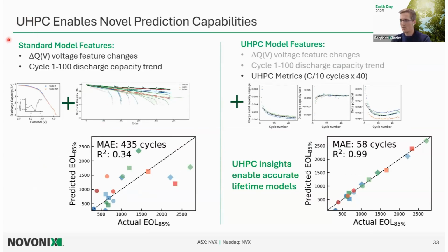So with standard modeling features, such as the residual voltage curve features from cycle 1 to 100, and cycle 1 to 100 discharge capacity trends, these are common features used in the literature, such as the Severson lifetime prediction paper. Especially with turning on and off all these different failure mechanisms, it gets very difficult to use these low resolution voltage curve features and degradation trajectories to predict the lifetime. And these typical models don't really work very well.